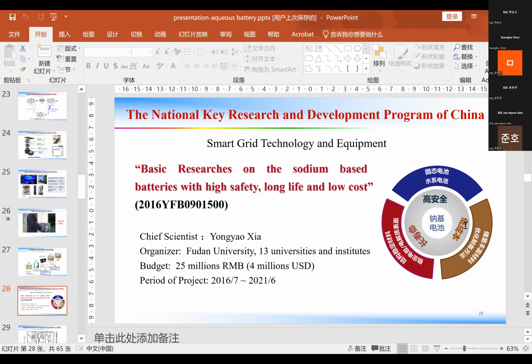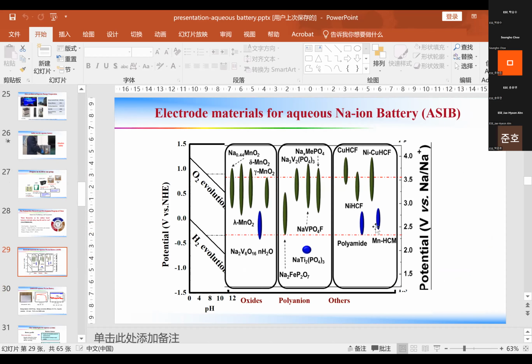We use low-cost materials. For the aqueous sodium-ion battery, we still have many electrode materials, but unfortunately most sodium cathode materials dissolve in the water. Really, we can only use Na0.44MnO2. This is a tunnel structured material. It is stable in the aqueous electrolytes, but most materials like sodium vanadium phosphate dissolve, and some organic electrodes also dissolve in the water.